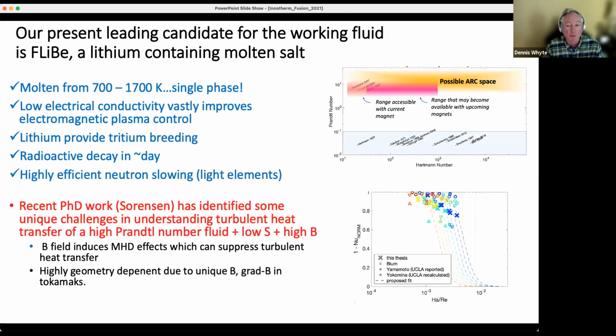We've identified some unique challenges because although it has low electrical conductivity, it's not zero. What we're finding is that it's sitting in a regime of Prandtl number versus Hartmann number that is almost totally unexplored in terms of heat transfer. So what's going to happen with turbulent heat transfer when you have a combination of a high Prandtl number, low electrical conductivity, and high magnetic field, on the order of 10 Tesla? What we're finding, over here on the right, is that the magnetic field is inducing MHD effects, which are starting to suppress the turbulent heat transfer. And this is highly geometry dependent, because the magnetic field topology of the tokamak is set by the plasma physics, not by the heat transfer. So you basically have to figure out clever things about how you're channeling flow parallel to B versus across B. There are also magnetic field gradients.